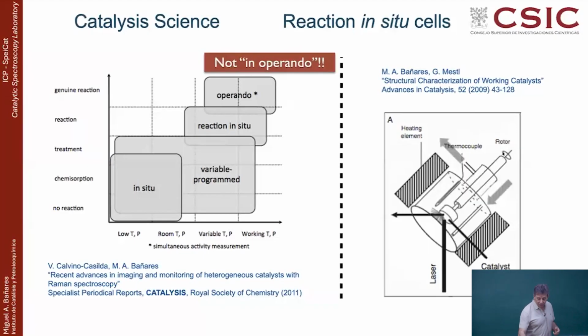But that doesn't mean you are really doing reaction, because when you go to the outlet of this in situ cell and ask the molecules about the reaction, most of the molecules will say, was there a catalyst? Because most of the molecules did not even interact with the catalyst. That tells you the big difference between in situ spectroscopy mimicking reaction conditions and in situ spectroscopy during genuine reaction conditions, where you determine activity simultaneously by measuring online, which is basically the idea of the operando methodology, because it means working.